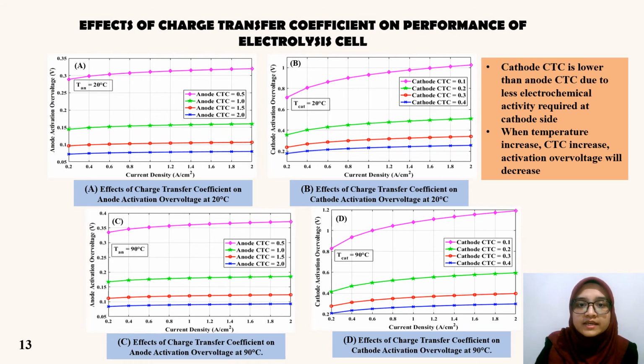For example, at the highest anode CTC of 2.0, the value of activation overvoltage remains the lowest at both temperatures. And the same thing occurs at the cathode side, where at the highest cathode CTC of 0.4, the value of activation overvoltage is also considered the lowest at both 20 degrees Celsius and 90 degrees Celsius.